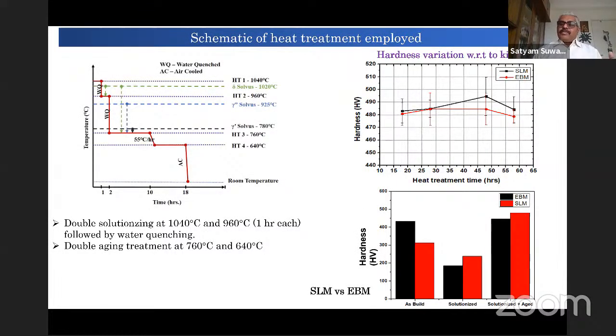Now, in the as-printed structure, we realized that the properties are not as appropriate as expected in the as-built condition, and the microstructure was also not good, so one has to apply heat treatments, which are anyway given to Inconel 718 even in the wrought and cast conditions. We realized that we need to apply modified heat treatment strategies for the dissolution of certain precipitates like delta phase, gamma double prime, and gamma prime. Considering all these parameters, we designed heat treatment strategies, and we indeed carried them out for both these SLM and EBM materials, and we could see the property differences and property stabilization for all these conditions.